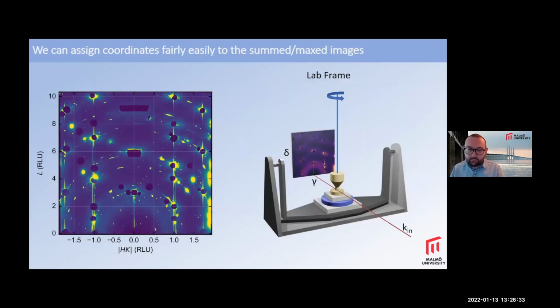And so what we can then do is we can assign coordinates to these combined images, and immediately get some information about what the structure of our sample looks like. In this case, this is a reconstructed gold 111 surface, and you can see rods at the integer spots due to the CTR, and then there's rods just at the side from the surface reconstruction. And this particular representation is independent of the rotation of the sample. So this is essentially your momentum transfer, your QR and QZ.